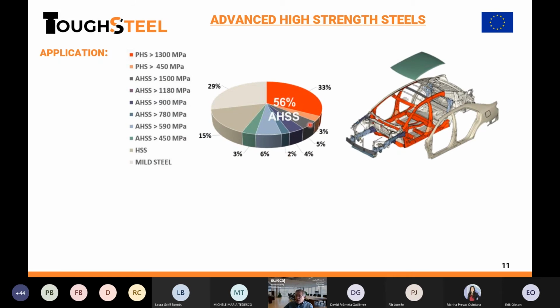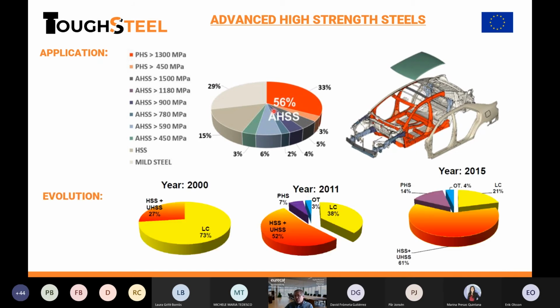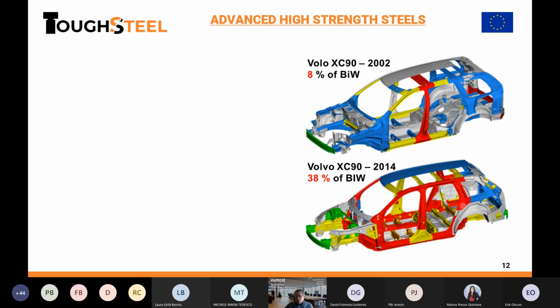Yeah, advanced high-strength steels are widely applied in the body in white. Here you have the different strength grades in different parts of the body, about 60% or even more for some vehicles. If you look at the evolution, 20 years ago in 2000, it was mostly low carbon steels and steels that in that time were called high-strength steels, but no more than 800 megapascals. If you look at the situation today, this is a breakdown for 5 years, but it doesn't change so much. We see the big introduction of press-hardened steels, and a big proportion of really high-strength steels, more than 800 or up to 1,000 or 1,200 megapascals of strength. So, just some figures to show you this evolution.